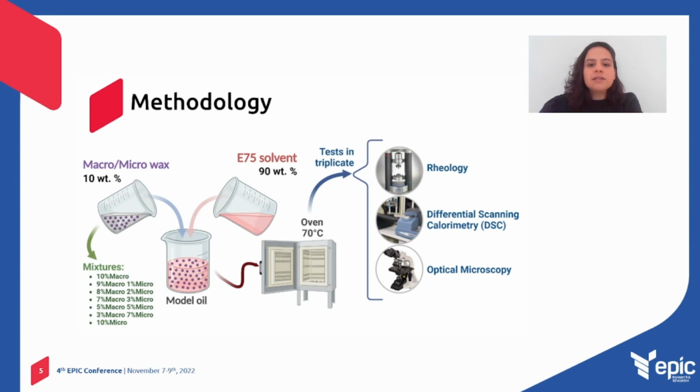And we analyzed these model oils with different methodologies. We did the rheology in rotational and oscillatory tests. We did the DSC, the differential scanning calorimetry, to analyze the wax appearance temperature. And we also analyzed the morphology by microscopy.